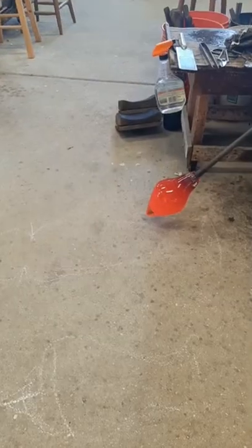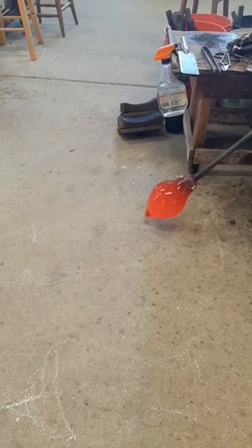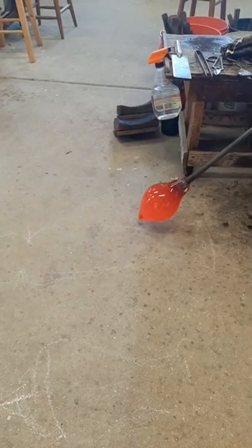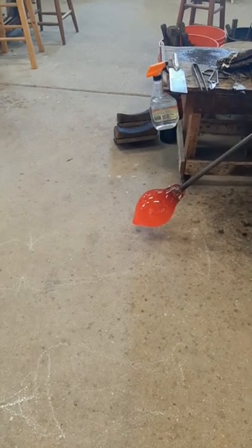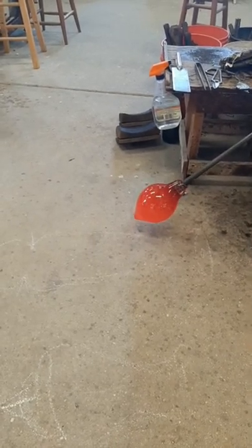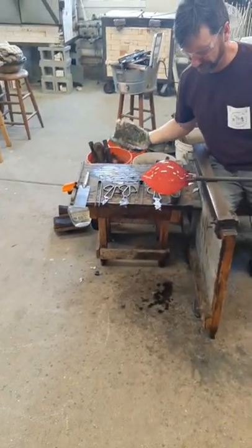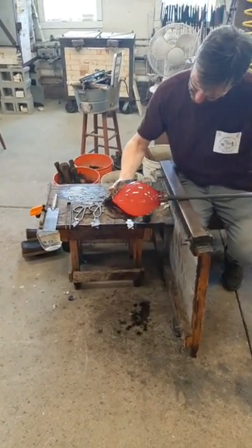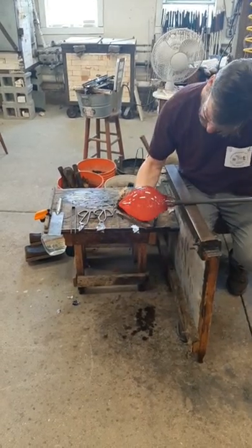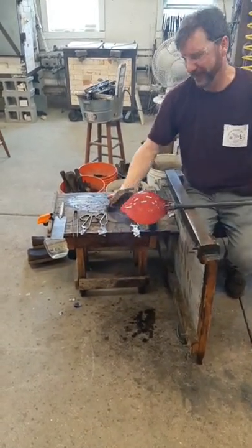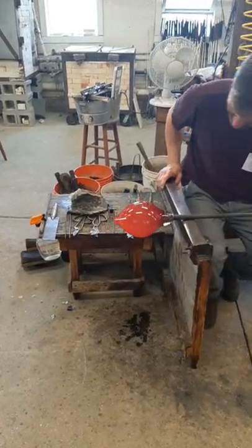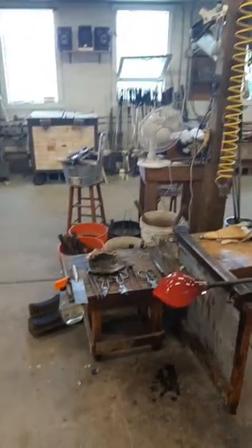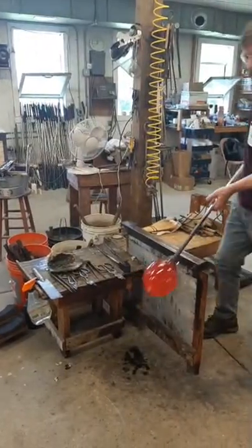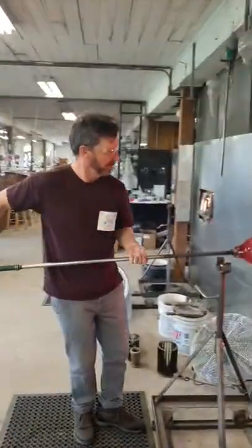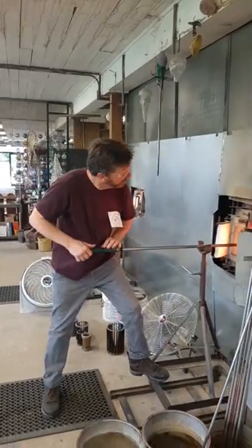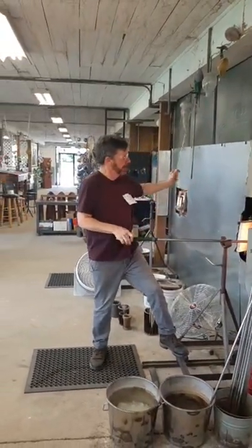He's blowing now, and look, that tip is not inflating at all. The whole piece is getting a larger diameter. Now I think this is going to be it for gathers, Rude. It's going to be a pretty good sized piece. So now he's got it inflated. And as we've said countless times, probably enough that you're tired of hearing it, 80% of our pieces are made by a sphere with a jack line. So once he gets the sphere pretty much enlarged, which I'm going to guess is right about now, he'll come back and begin initiating a jack line.